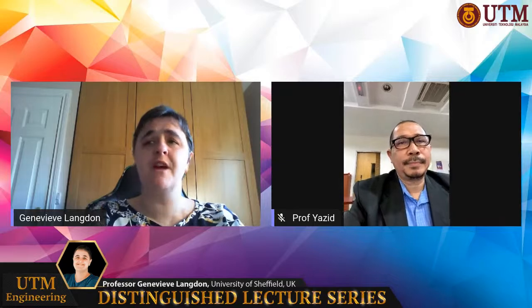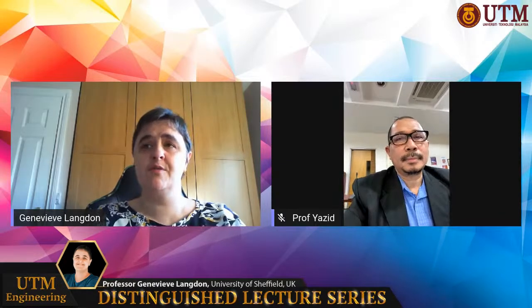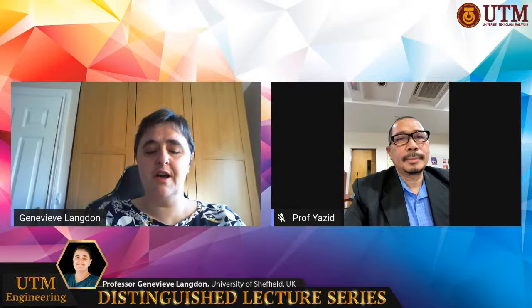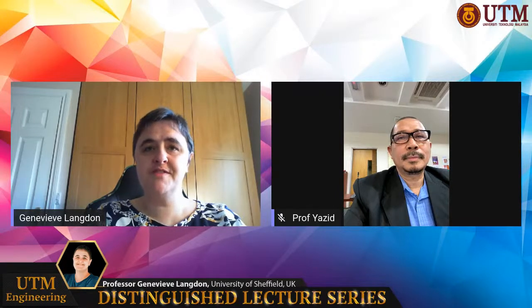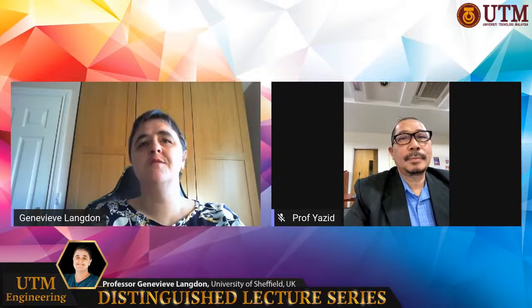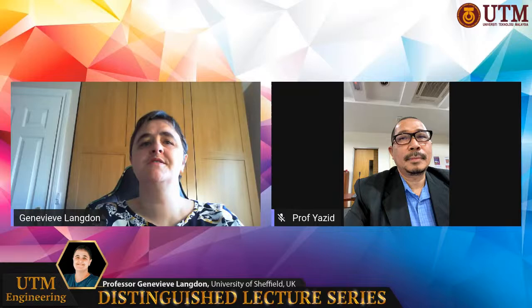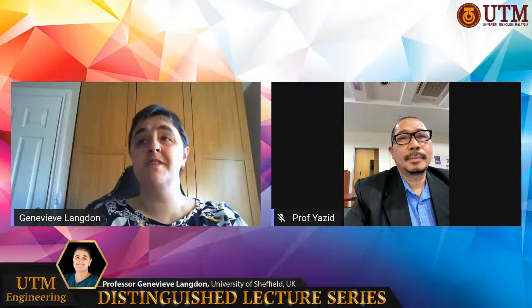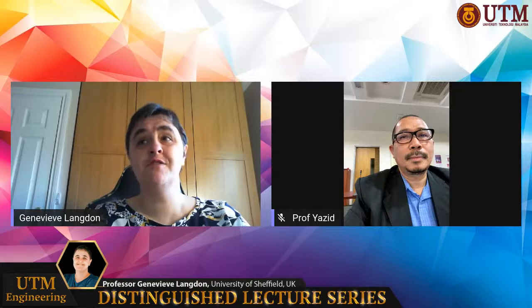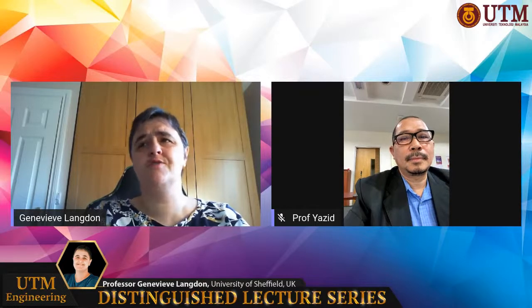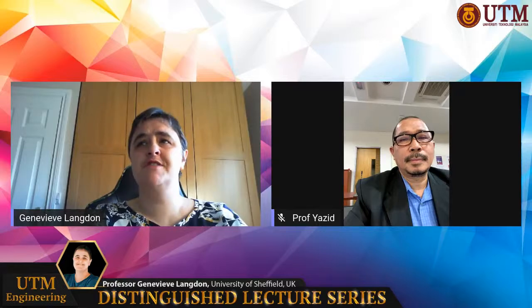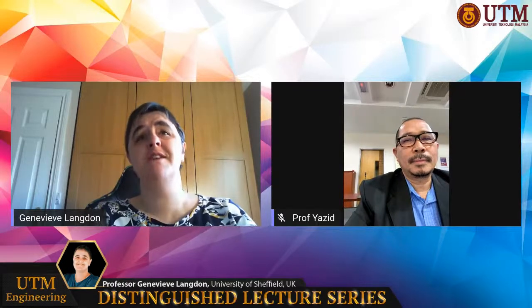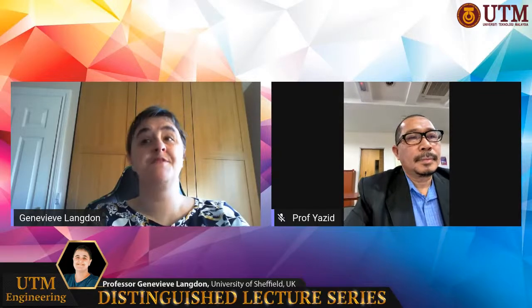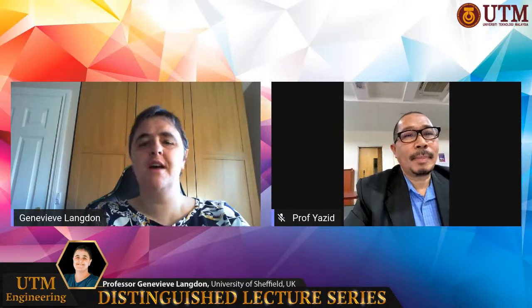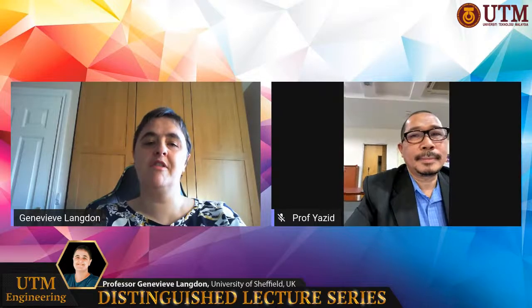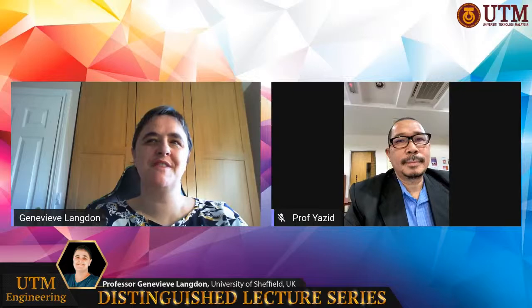And then the second thing that you have in an explosion that you don't have in a quasi-static type of experiment is strain rate sensitivity of the material properties. So some materials have high strain rate sensitivity, such as steel. There's some debate about whether glass fiber has high rate sensitivity or not. And some materials have very low strain rate sensitivity. So for example, stainless steel has less rate sensitivity than mild steel, but it still has some, and some interesting ones depending on the grade of stainless steel. And then carbon fiber and glass fiber potentially also have different rate sensitivity effects.